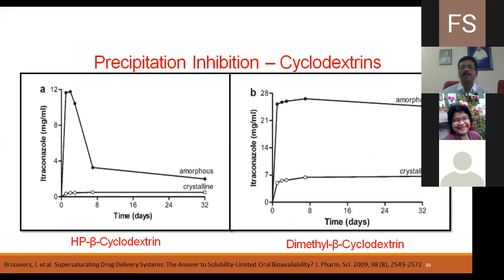Now we shall take two cyclodextrins and observe their effect. The drug is itraconazole, and the two cyclodextrins were HP beta cyclodextrin and dimethyl beta cyclodextrin. The data are interesting, and they demonstrate two principles in the formation and stabilization of supersaturated drug solutions. In the case of HP beta cyclodextrin, the complexation efficiency is relatively low, such that relatively high levels of supersaturation are generated, which fall as a function of time.